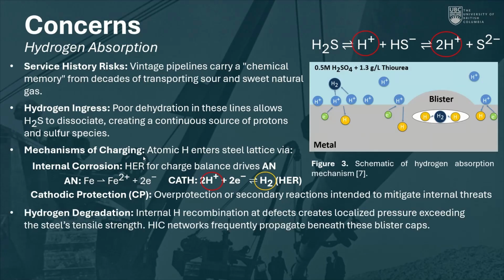And what does that look like? So essentially, if we look at the cathodic reaction, before hydrogen gas, H2, is formed, we have single atomic hydrogen atoms. So just single H's essentially being adsorbed on the steel surface. And when two of them combine, they form hydrogen gas. But just before hydrogen gas is formed, those single H atoms can diffuse through the steel lattice. And specifically, they can accumulate at defects, which over time can build its own partial pressure within that steel. And if that exceeds the steel's tensile strength, we may see blistering or hydrogen-induced cracking propagate within the steel.